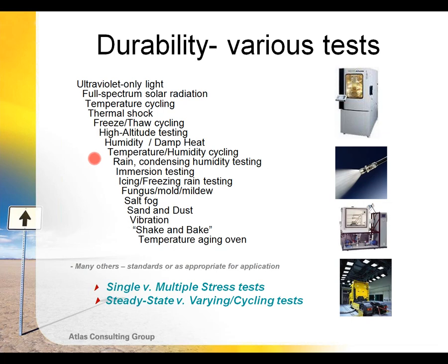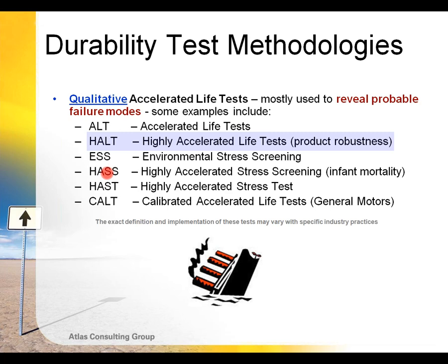Then determine the likelihood of those. Identify simple tests to try to test for those. And then, based on those results, see if we need to step up to looking at combination or interaction effects, and then also be very important to look at interaction or interlayer effects, especially on a manufactured product, which may be a composite or laminate in terms of its construction. Because very often we can have migration of chemical species through different layers that would not be caught in testing the individual materials by themselves.